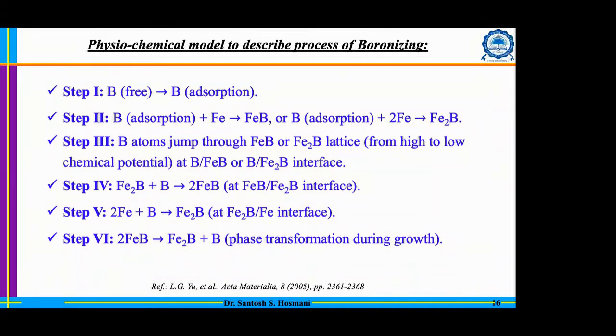You have only Fe2B. Then there is the migration of this boron across the interface of boron and compound layer. And then finally, these borides will grow. Now the growth, the morphology, again depends on the crystal structure of these borides that I will discuss later. And as you know, initially there is a formation of Fe2B. And then subsequently, at a later stage of boronizing at the surface, there will be the consumption of Fe2B, and that will lead to the formation of FeB.